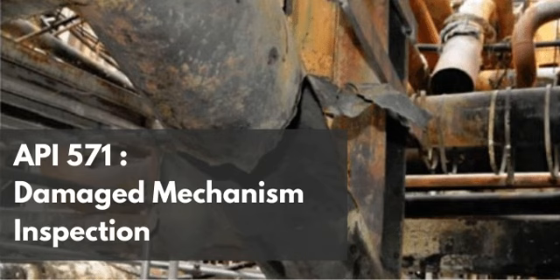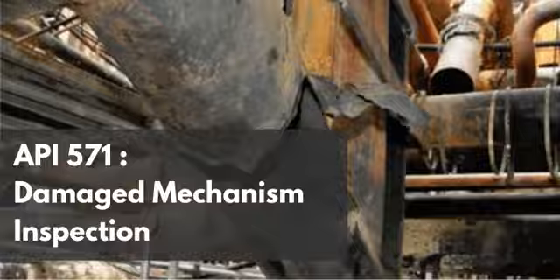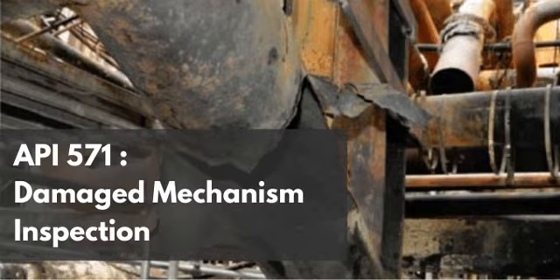Let's look at the alternatives provided by the API text. Because if non-PWHT'd carbon steel is fundamentally vulnerable, there are going to be times when engineering requires a total bypass of that risk. Sure, when you just can't risk it. The text lists solid or clad stainless steel or other corrosion-resistant alloys, commonly known as CRAs. Why does changing the alloy completely shut down this specific cracking mechanism? It really comes down to the fundamental crystallographic structure of the alloy.